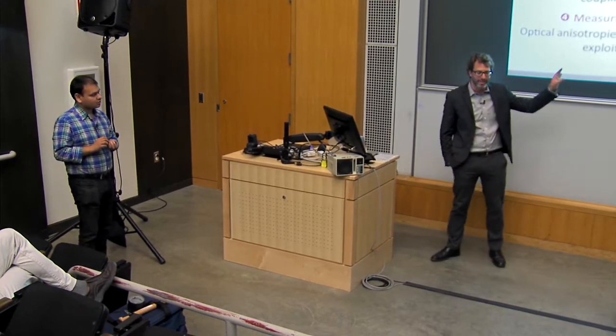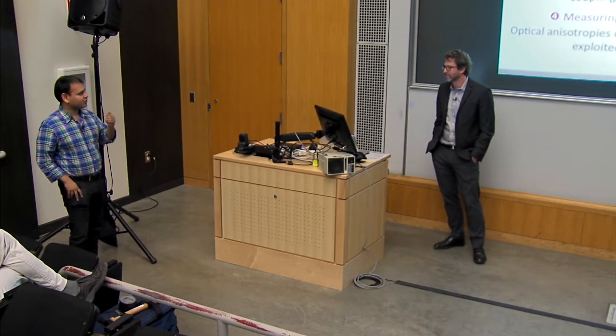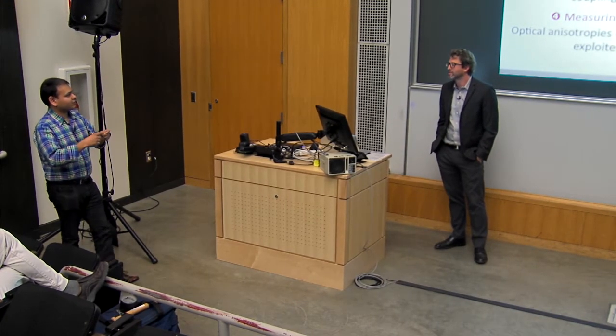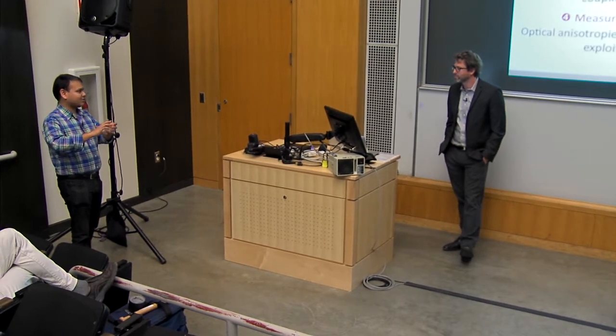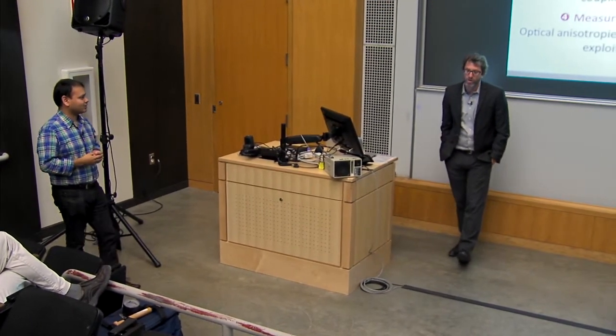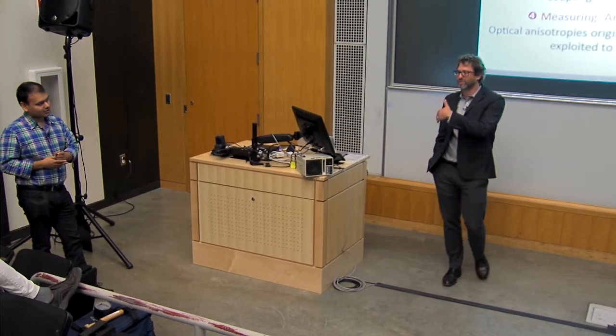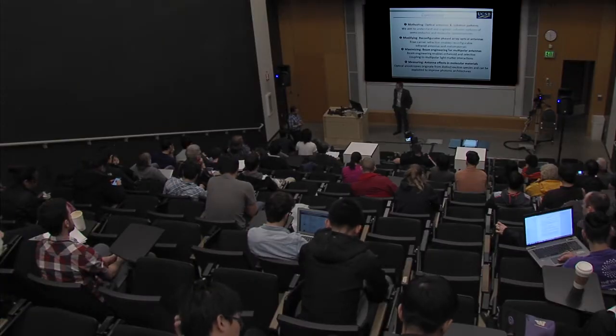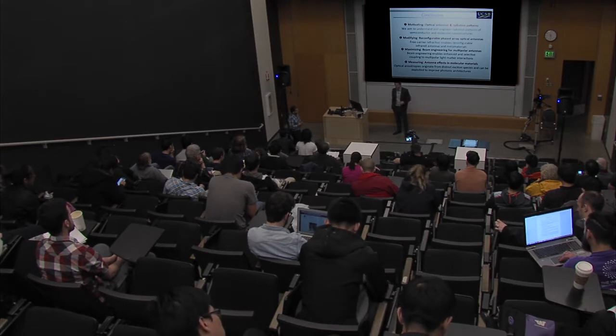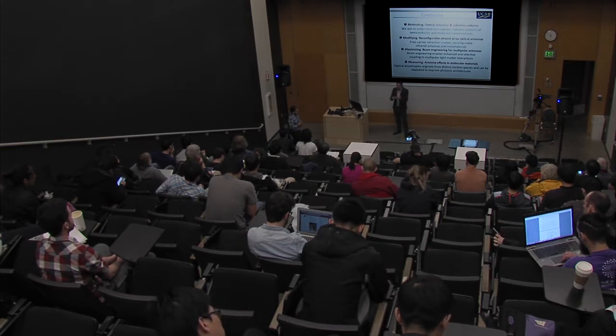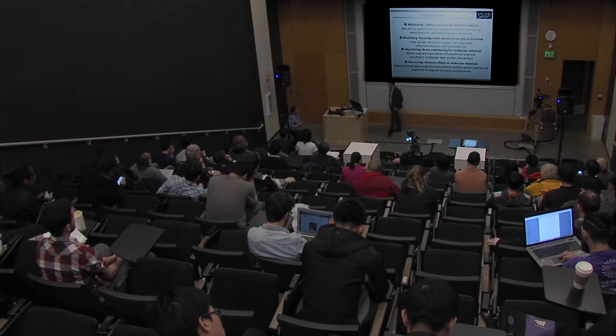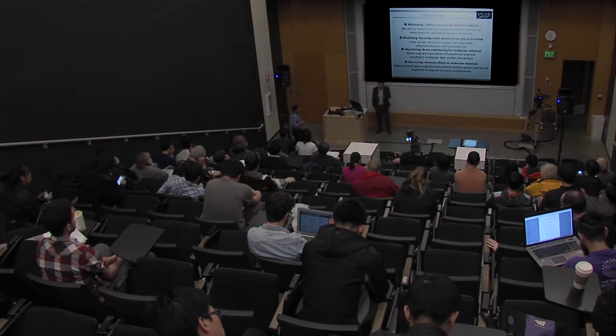But actually, we're more interested now in the electrical injection method. I think it depends on the intrinsic doping. Like if you're, at least for the silicon photonics, it depends on intrinsic doping, and you can change by only a certain ratio, like maybe 100 and 200. But yeah, so the intrinsic doping will, to some extent, control the lifetime of the excitations. Yeah. Now, in this case, once you get to high enough carrier concentrations, if the carrier concentration is much larger than the intrinsic doping, then whatever your starting level is doesn't matter so much. Okay. But I think it'd be pretty hard to do optically, so we're moving towards the electrical injection method. Okay. Yeah.